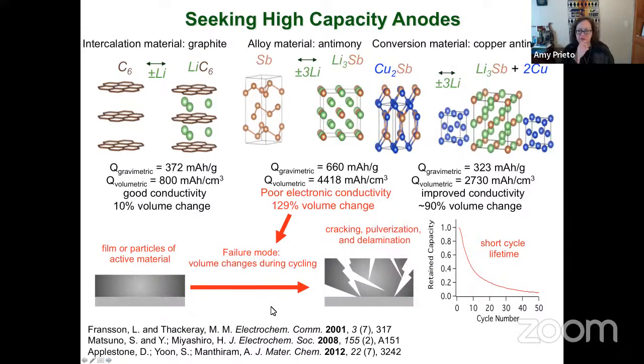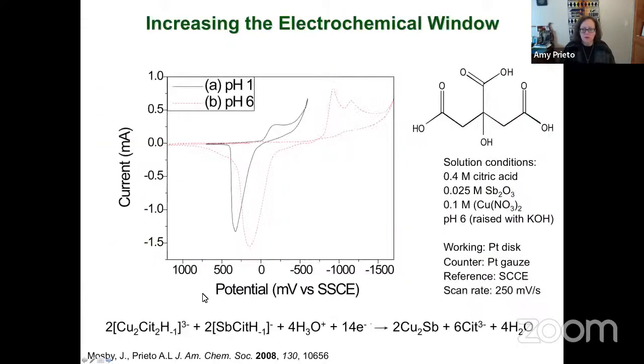If we move, however, to something like copper antimonide, we still make the same daughter compound, Li3Sb, but now you extrude 2 moles of copper, which act as a conductive matrix. There is a trade-off in terms of the gravimetric and the volumetric capacity, but the volumetric capacity is still significantly higher than what you would get with graphite. The films are much better in terms of conductivity, and the volume change is a little bit more modest. So we decided to focus on that as our first anode.